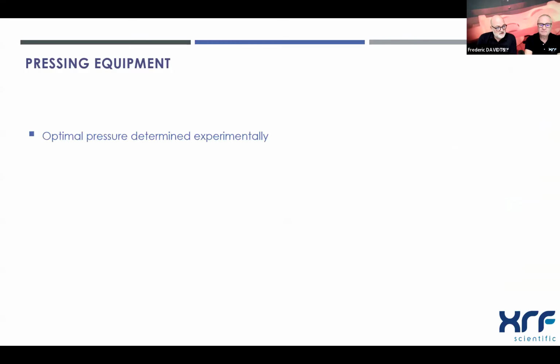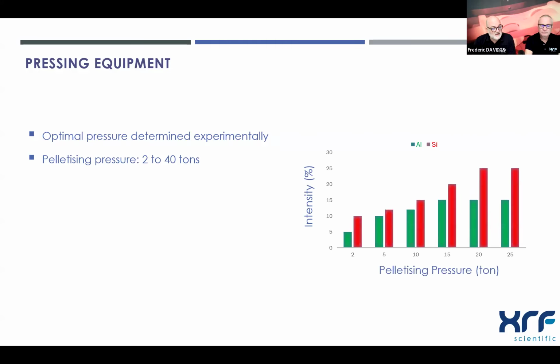So the pressing equipment. Just speaking about the pressure, which pressure to use, most of the time is determined experimentally. So normally between 2 and 40 tons. And what we try to find is, when we can see on the graph, the intensity versus pressure for aluminum and silicon, what we want is that the good pressure will give the highest intensity for most of the elements of interest, of course. And we need to press up to obtain this plateau, and no need to press at the maximum if we can reach the good intensity peak for the element we are interested in for sure.